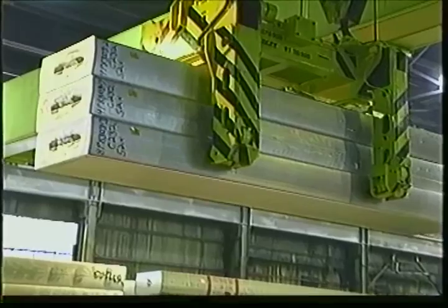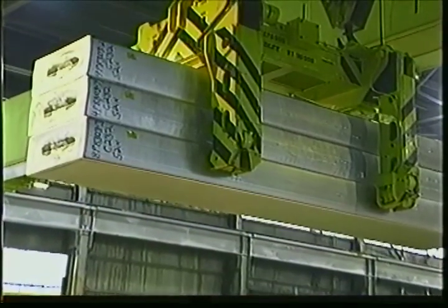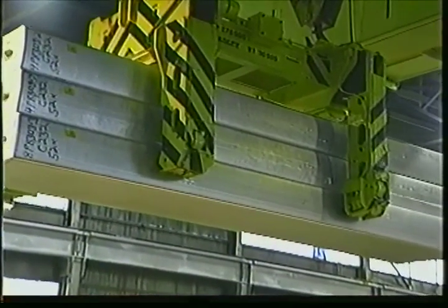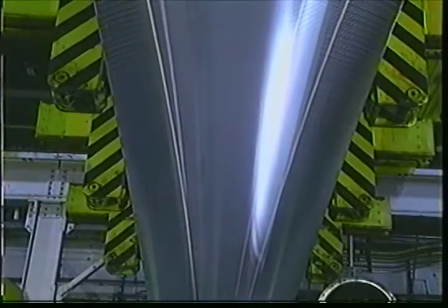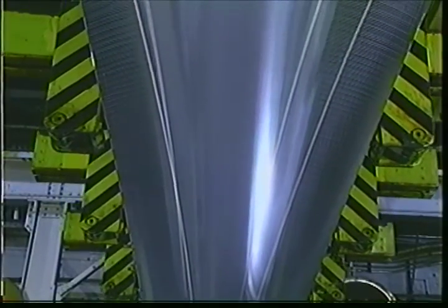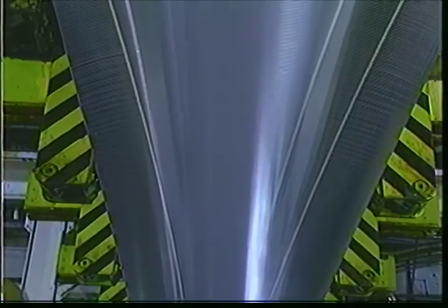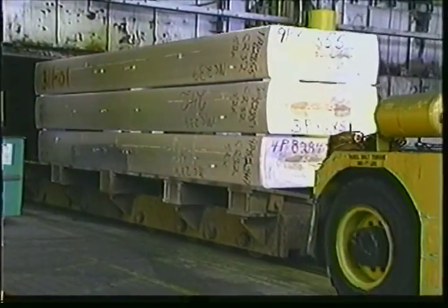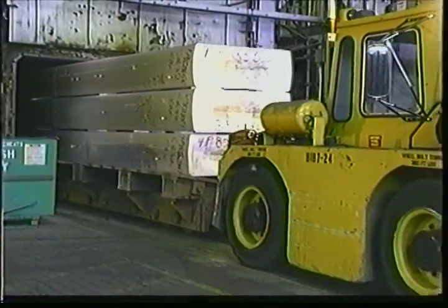Ingots, which weigh up to 40,000 pounds and are 30 feet long, are then transported to the scalper. Here, the ingot's top and bottom layers are literally shaved to form a mirror-like surface. Scalped ingots are then transported to the preheat furnace to make it pliable once again for hot rolling.